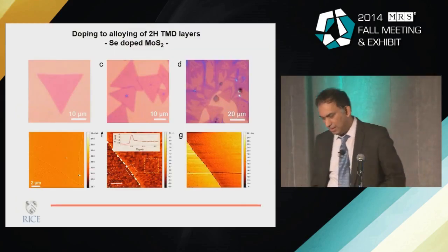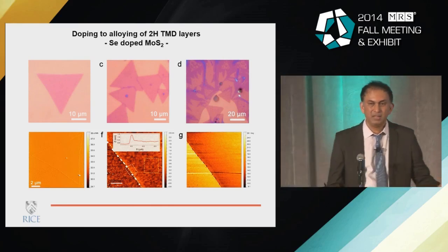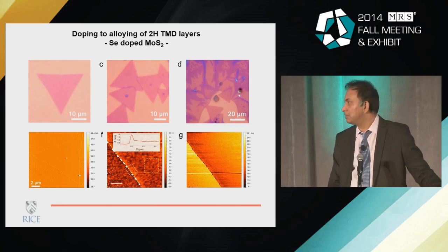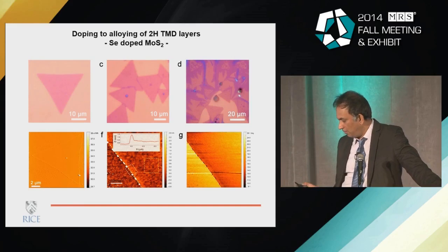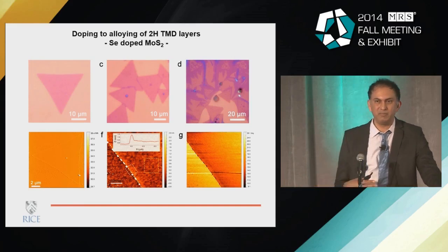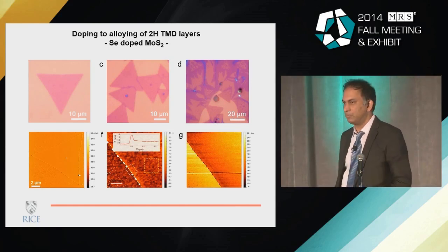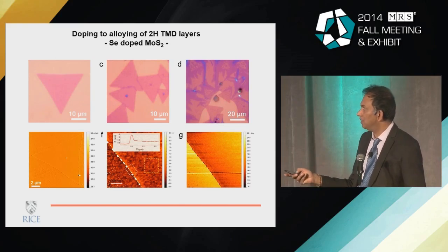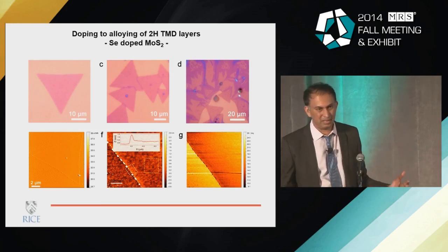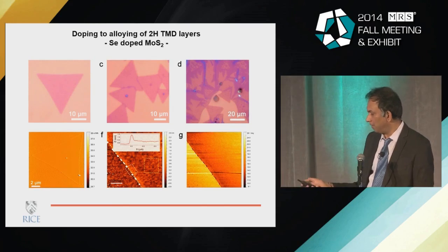Now, doping is also very much possible, and people have shown doping in transition metal dichalcogenides in nanoparticles, other systems of TMDs. Even in this monolayer, doping is certainly very, very feasible. And unlike the graphene system where the dopants were segregating into domains, here there's a very nice uniform distribution of dopants throughout the system. This is an example again of selenium replacing sulfur, and the replacement could be almost complete. You can actually get the entire spectrum of concentration change from molysulfide to molyselenide.